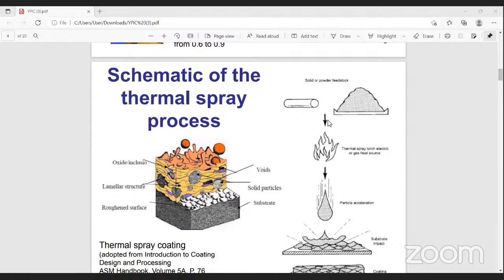The formation of thermal plasma coating is characterized by the ingress of large numbers of particles, more or less melted in the plasma jet, forming so-called splats, between which pores are formed. Herewith, the porosity and roughness of the coating surface depend on the size, speed, and degree of heating of the particles forming it. The pore size is affected by both the actual size of the coating particles and their shape. Understanding the mechanisms of coating formation allows selecting specific parameters of thermal plasma spraying to obtain the desired microstructure of the coating.